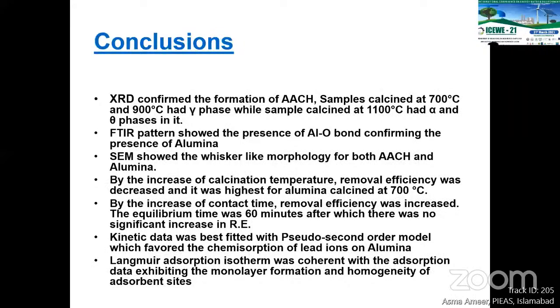By the increase of calcination temperature, removal efficiency was decreased, and it was highest for alumina calcined at 700 degrees C. By the increase of contact time, removal efficiency was increased. The equilibrium time was 60 minutes, after which there was no significant increase in removal efficiency. Kinetic data was best fitted with the pseudo second order model, which favored the chemisorption of lead ions on alumina. The Langmuir adsorption isotherm was coherent with the adsorption data, exhibiting the monolayer formation and homogeneity of adsorbent sites.